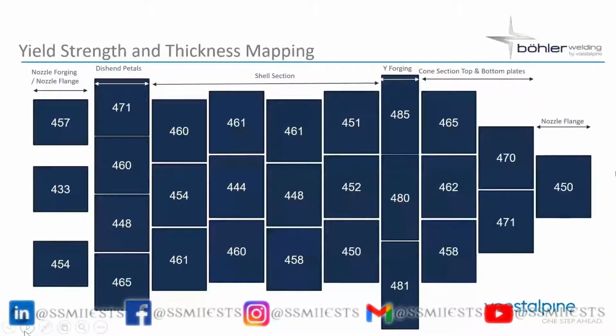So this is a schematic diagram of an actual mapping that was done by the fabricator. On the left side, which is actually the bottom, you have the nozzle forging. Then you have the dished petals, the shell section, the Y forging, and as you can see, the plates have been selected based on their yield strength so that there was not too much of a variation in yield between plates on different sections next to each other. So, for example, for the dish and petals, you have between 470 to 450, and towards the other side, in the cone section, you have 465, 458. Next.